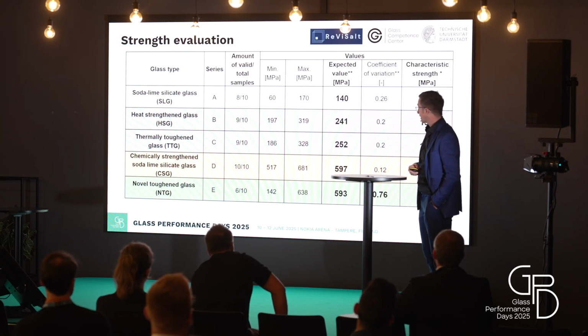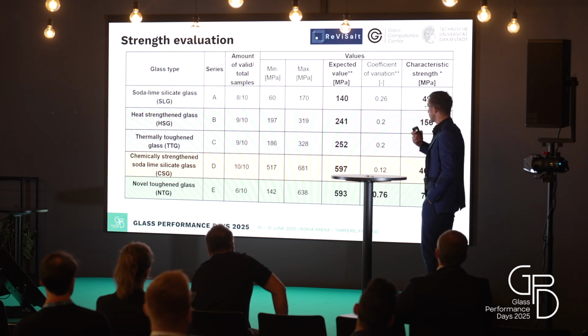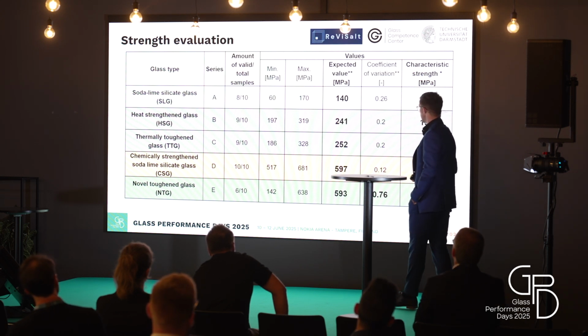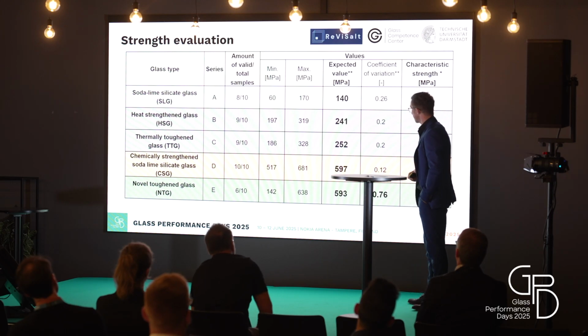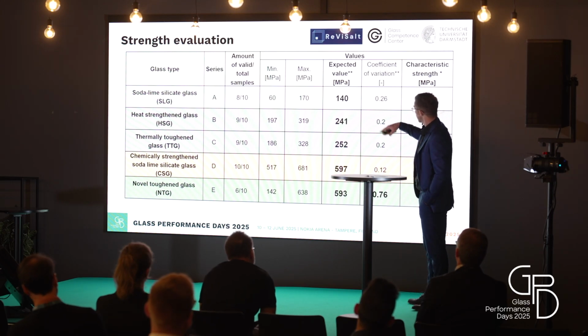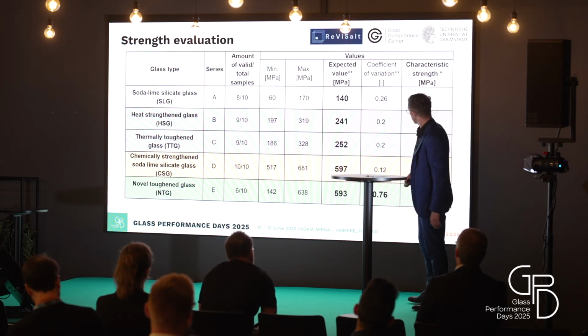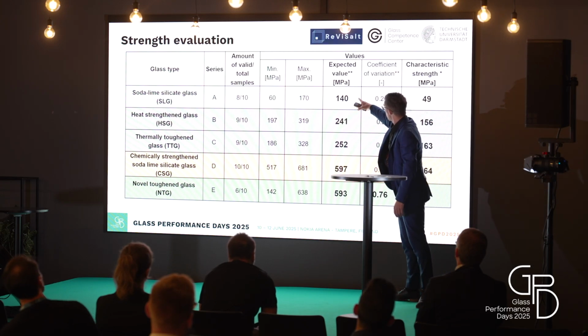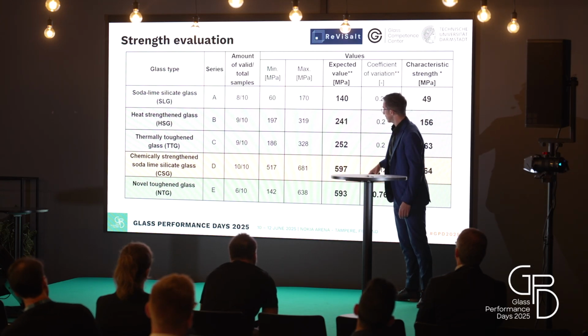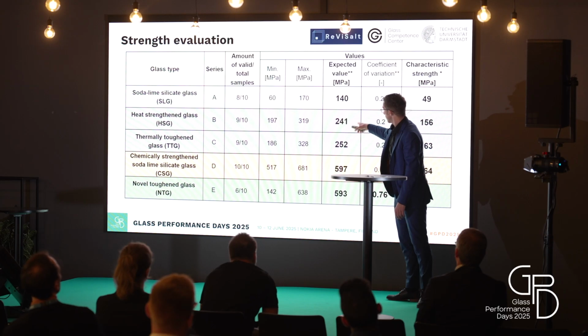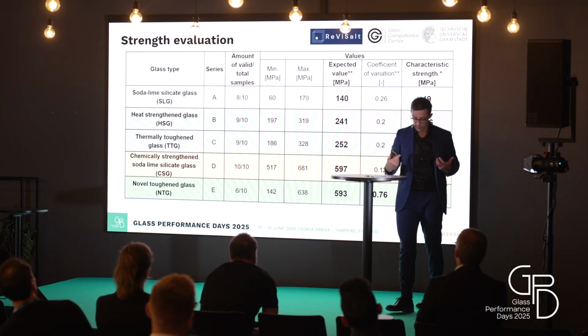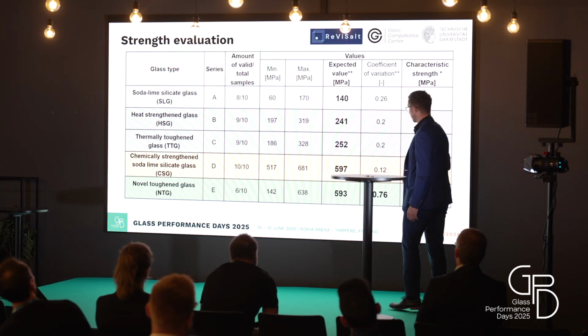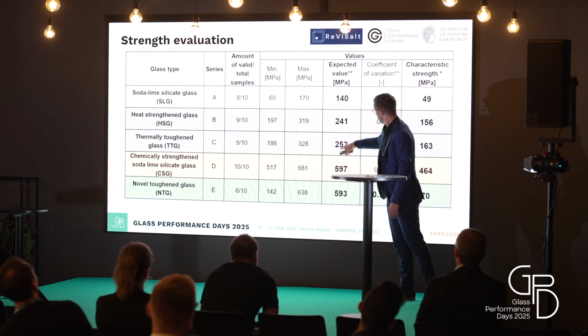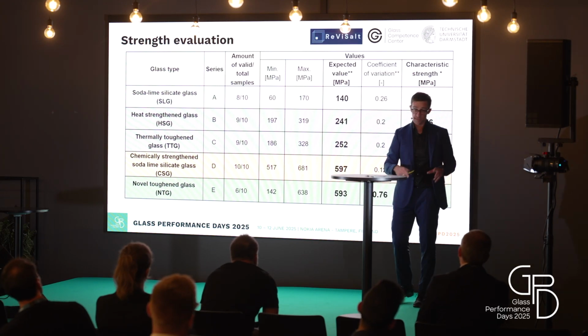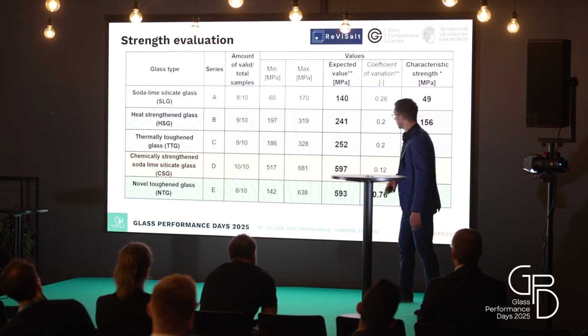Okay, now I come to the values. We do some statistics, two-parametric Weibull distribution. These are the expected values, like the mean value. Here we are in the typical range of the soda lime glass for this load ring configuration. Here the normal part for the thermal pre-stress, here 240, also here we are 250, here 600 more or less for the chemical one. And for the novel toughened glass, we are also in the region of 600.